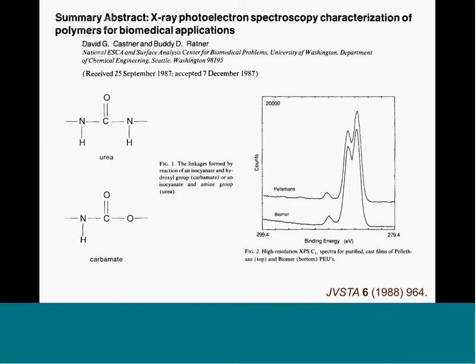Just to put this in context: a year after that first biomedical surface analysis meeting I attended, I'd just been working at the University of Washington for a month, so I didn't have anything ready to present. But the next year was my first biomedical surface analysis presentation—to no surprise, XPS characterization of polymers for biomedical applications. We were looking at subtle differences in C1s binding energies of carbamate versus urea carbon, and really trying to understand how manufacturing additives such as lubrication waxes affected the surface chemistry of polymers.